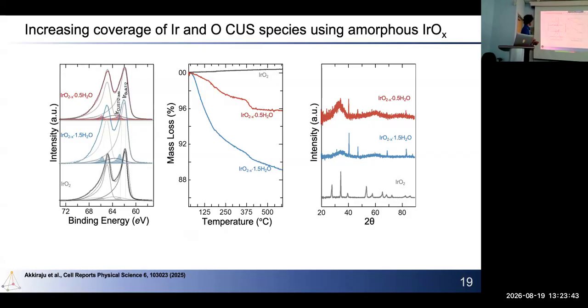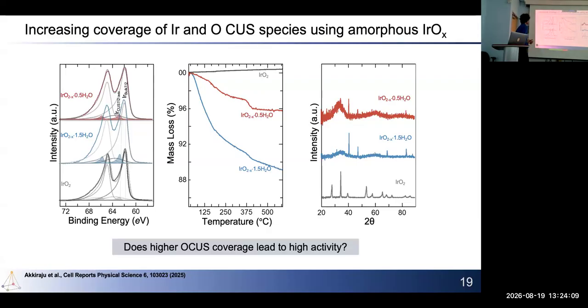So the one shown in gray is the one that we had been working with so far. We then designed two other iridium oxide species, shown in blue and red, with higher iridium and oxygen CUS species content. We characterized them using XPS and then XRD to make sure that we do have these CUS species. And then we want to test them out in a reactor setup to see if we could activate methane at a lower temperature.